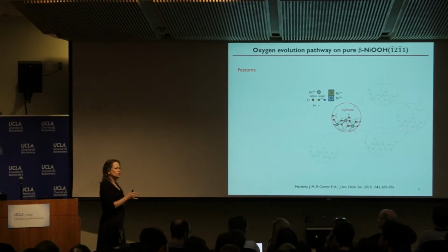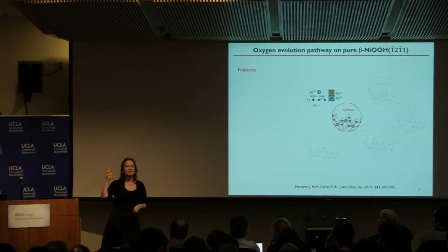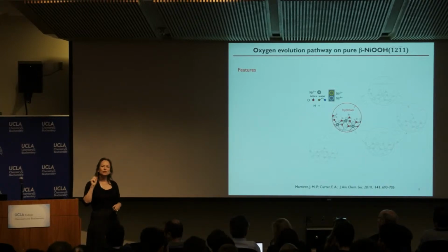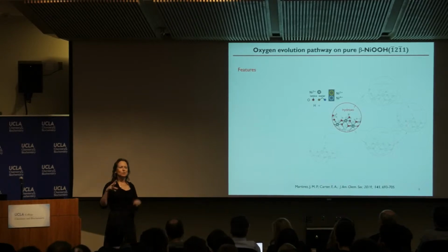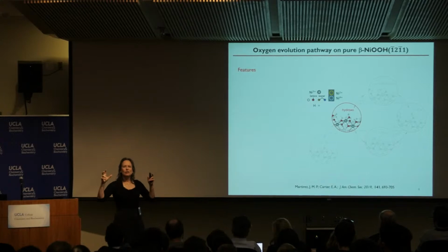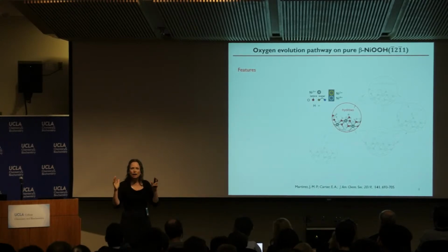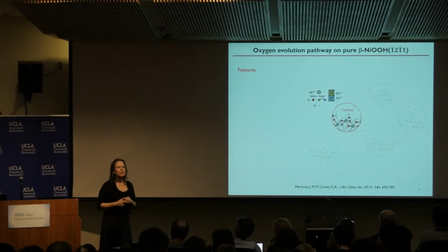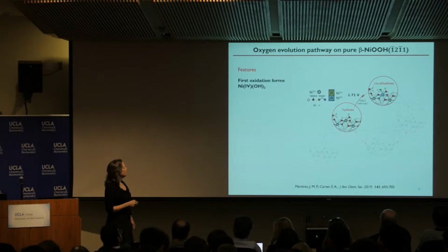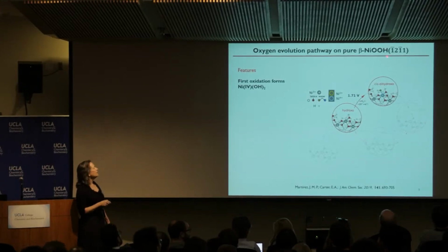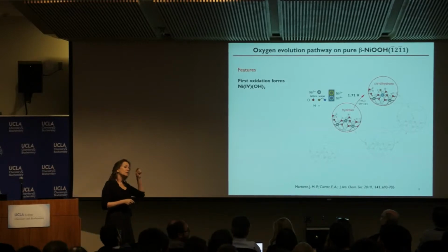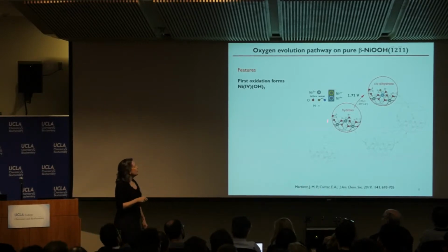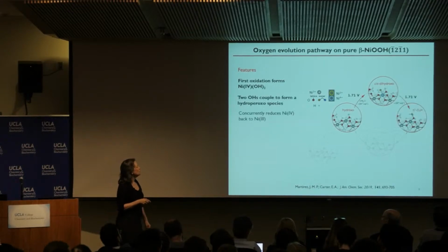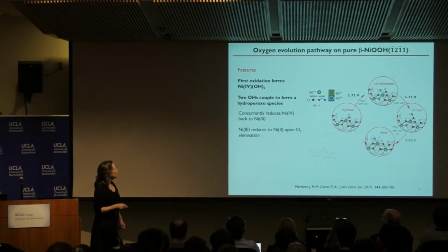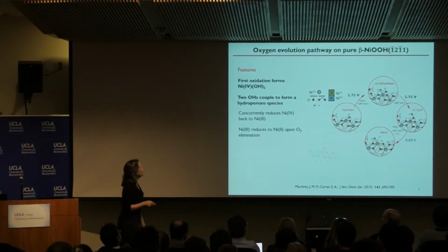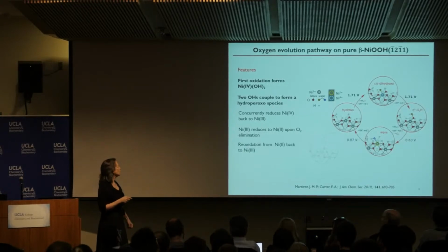Well, it turns out, you might think, well, it's just because you substituted iron, and iron is somehow fabulous, right? That's part of it. But it's not that simple, because it turns out it doesn't go through the same mechanism. So again, this is beautiful chemistry showing that you have to not just look at one mechanism, but a multitude of mechanisms to try to figure out what's really going on. And Mark did that, and what he showed is that, in fact, the most favorable mechanism for the pure nickel oxyhydroxide doesn't go through that metal oxo species. Instead, the oxidation produces a dihydroxo species that then makes a hydroperoxy species, which then releases O2. So a completely different process of redox chemistry than what goes on in the case of iron.